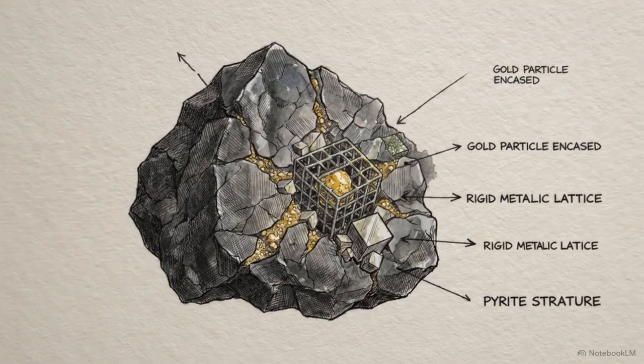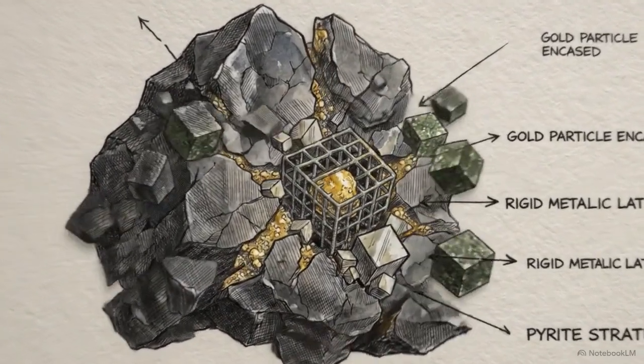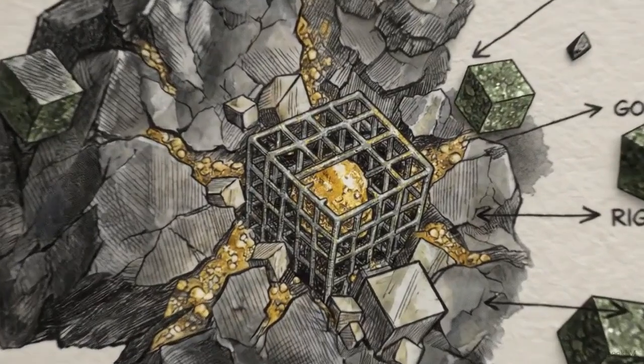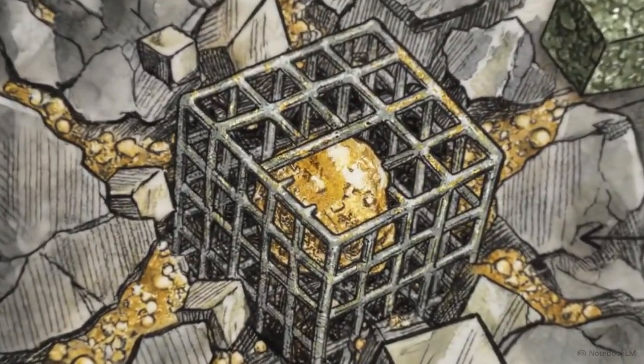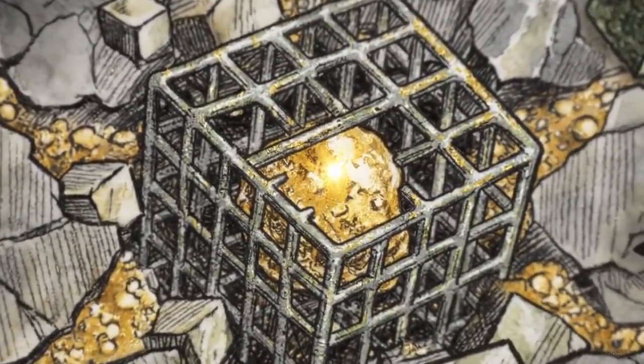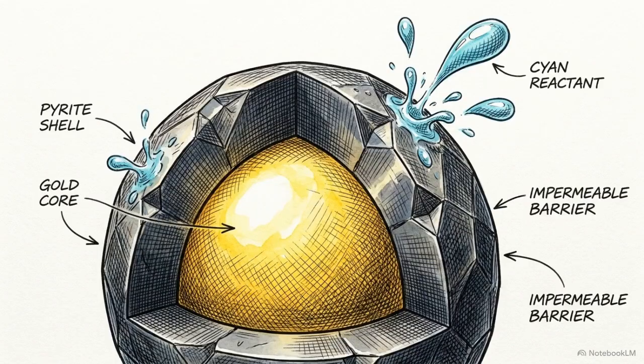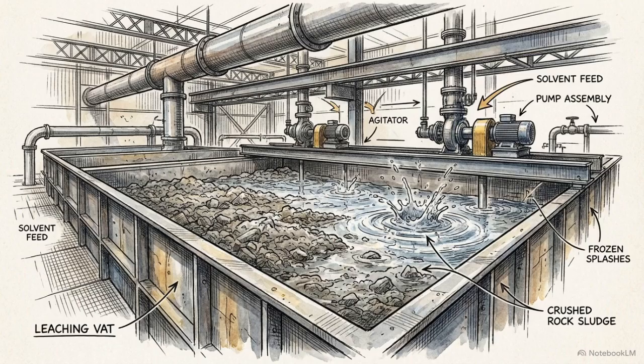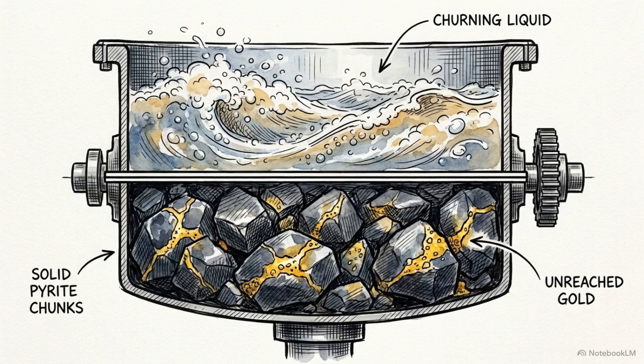High-sulfide gold ore presents a specific metallurgical challenge. In these deposits, 20 to 30% of the gold is locked inside sulfides, primarily pyrite. Because the gold is encased within these rigid metallic structures, standard extraction chemicals cannot physically make contact with the gold particles. Attempting to process this raw rock using a standard direct cyanide leaching circuit results in the chemicals washing over the pyrite armor, leaving the gold untouched.